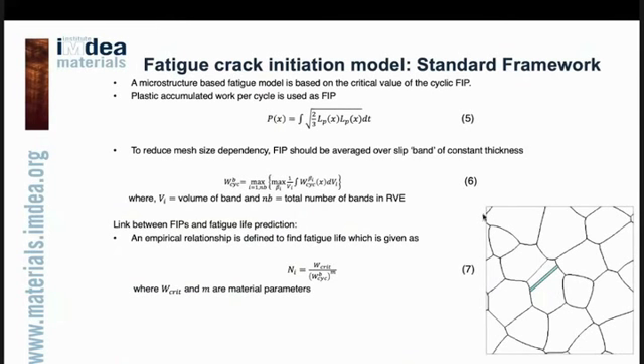Now the fatigue characterization model is based on identifying the critical value of cyclic FIP. Let's say this is the microstructure. In order for a crack to initiate, whichever point has the maximum accumulated plastic work per cycle, in short FIP, at that point we say that a fatigue crack has been initiated. We consider different bands, like I show in the figures, to reduce the mesh size dependency, and these bands are oriented along all the slip systems. Once we have the FIPs, we establish an empirical relationship between the FIP and the fatigue life through two parameters, the critical FIP and the M, that we need to fit in further work.